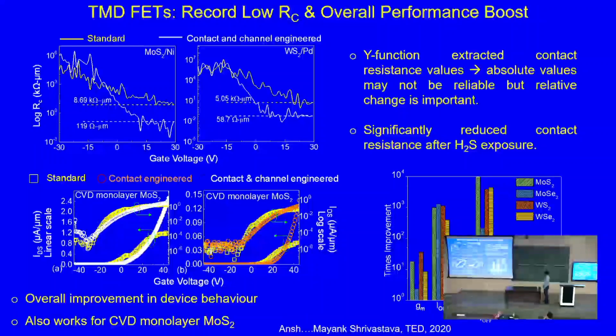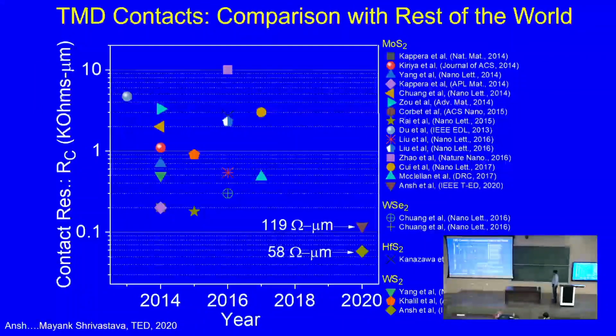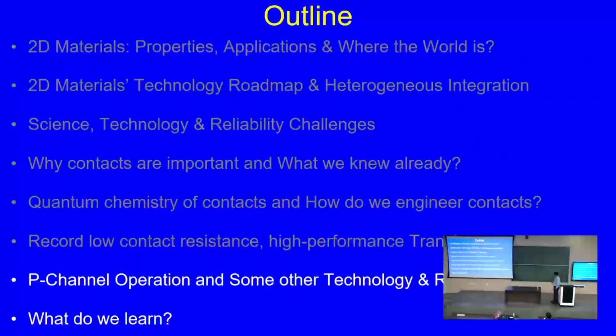And we also demonstrated this further on CVD monolayer, and reported contact resistance in the range of 58 ohm micrometer for WS2 and 120 ohm micrometer for MoS2. Now you remember the quantum limit is somewhere in the range of a few kilo ohm micrometer, and we got in the range of 100 ohm micrometer. So this is where we are in terms of the TMD contacts, far below the best reported numbers from around the world. Now what we also did, we also demonstrated p-channel operation.